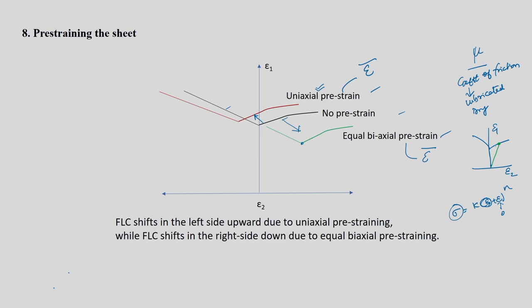Or you put any lubricant you want, and you change the lubricant to some other lubricant. We don't know the characteristics of the lubricant, we don't know mu, but if that is the situation, one can still study the effect. For one particular case, you will reach a forming limit here. If you change the lubrication, let us say lubrication is better, then you may get a higher limit strain, a better epsilon 1 star and epsilon 2 star value as compared to the previous one, but it will reach the same forming limit.